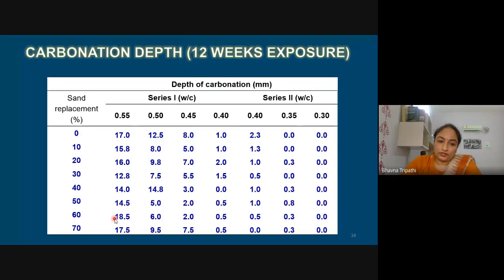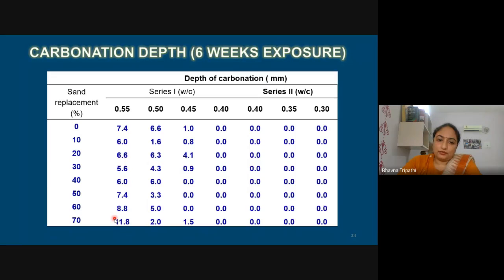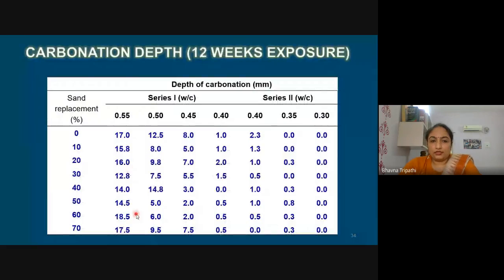What we can observe is that initially this mix at 6 weeks had higher than control. However, later on, the depth of carbonation in control mixes was higher, and all the specimens which had isoslag showed depth that was less than or very, very similar to the control specimen. This again was very encouraging.